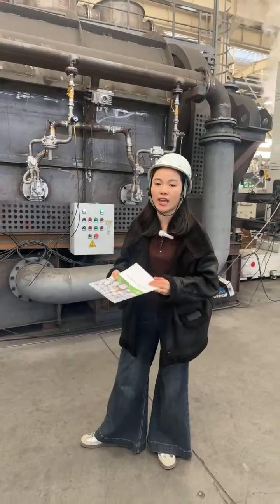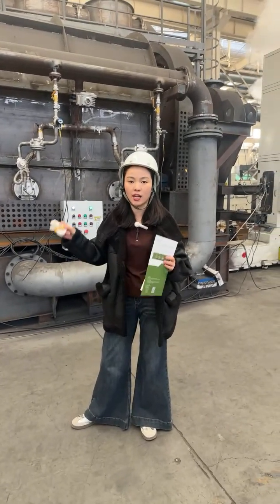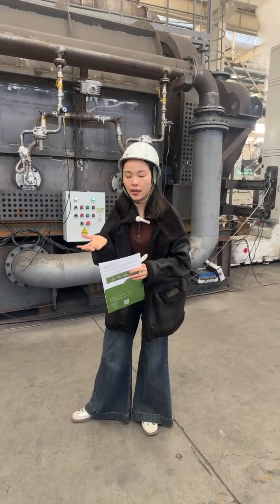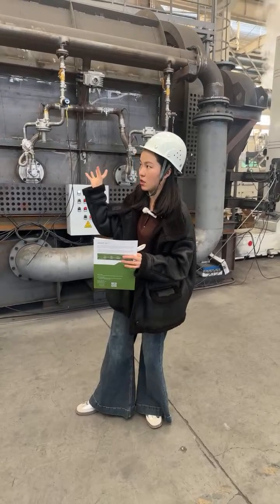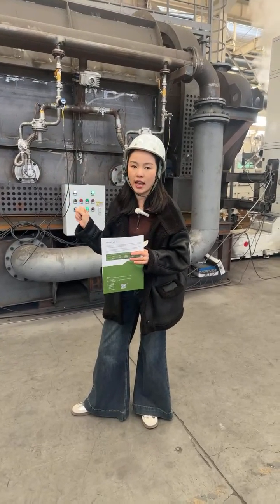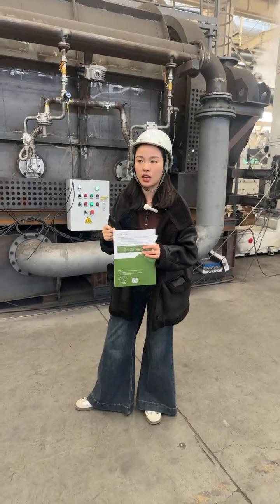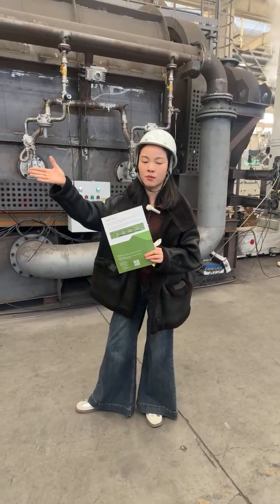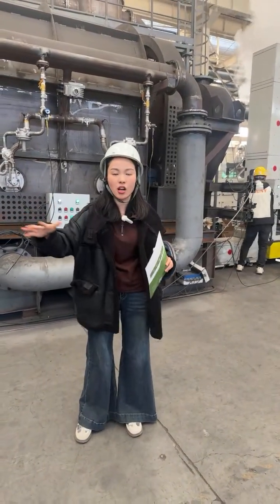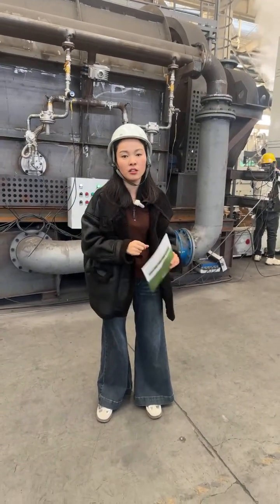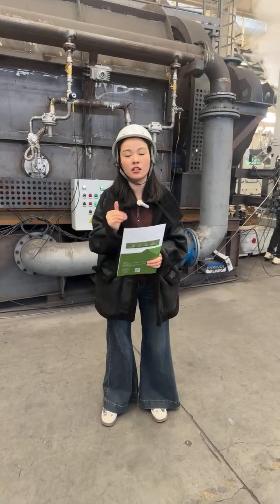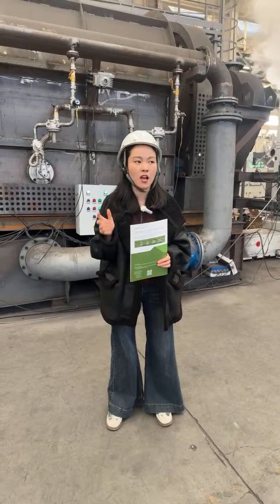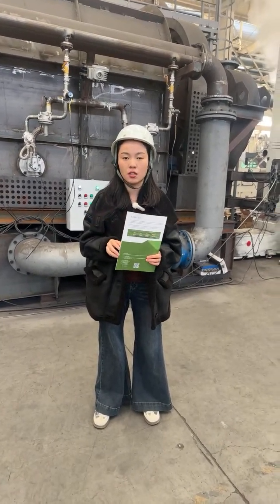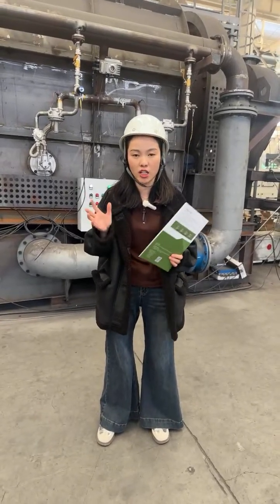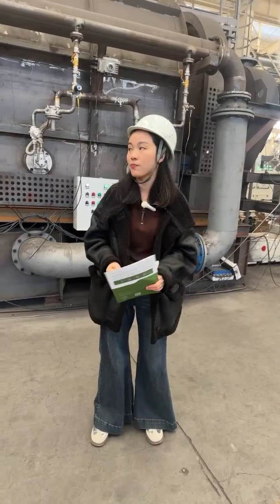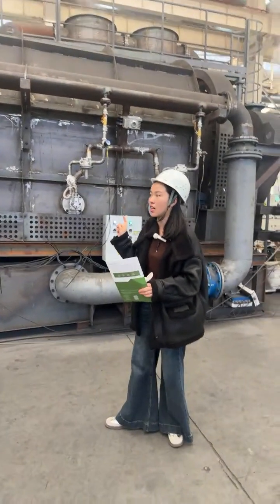So with this furnace, we can get the electrolyte fully evaporated into gas. So the electrolyte will turn dry, and we can also collect the VOC gas for exhaust gas treatment. Otherwise, if you don't use the furnace, the electrolyte will keep evaporating from the beginning to the end, so there will be harmful gas from the beginning to the end. That will be a very big headache, especially for some highly developed countries. Most countries have very strict requirements on exhaust gas treatment. So that's the first reason for us to use the carbonization furnace.